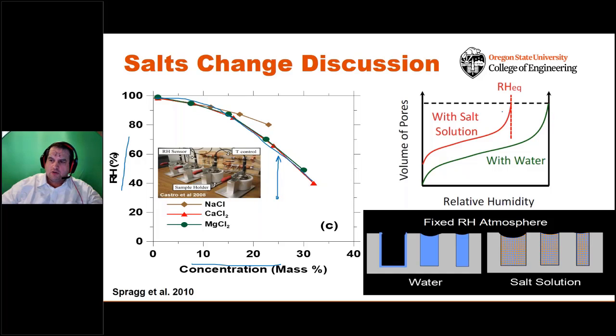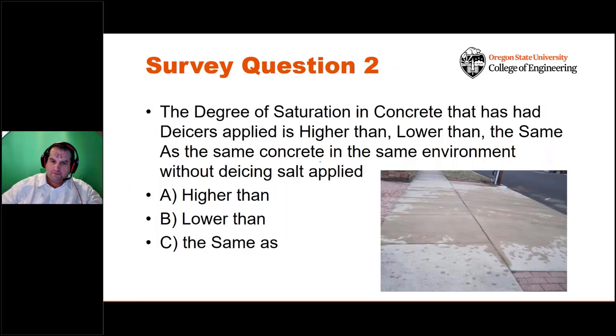So what this means is when you've got a salt inside of your system, you're going to have concretes that stay saturated for a much, much longer time. We don't get the evaporation that's taking place. So if you have, for example, 25% magnesium chloride sitting in the joints, which is very, very possible, drying doesn't start to take place until you drop below 60% relative humidity. Above this, you're going to see moisture just getting sucked into the overall system.